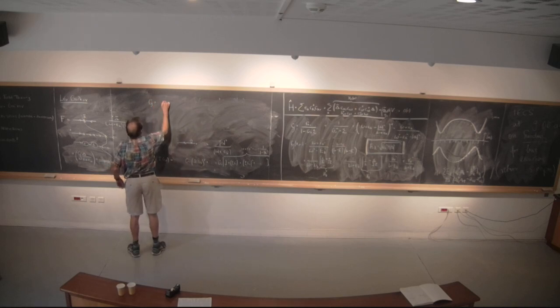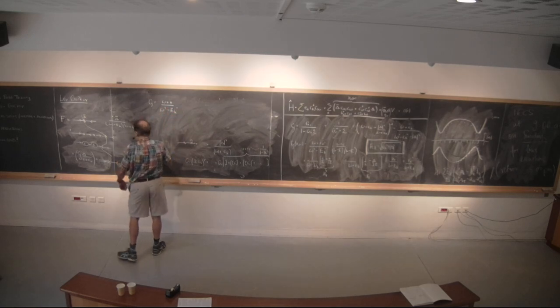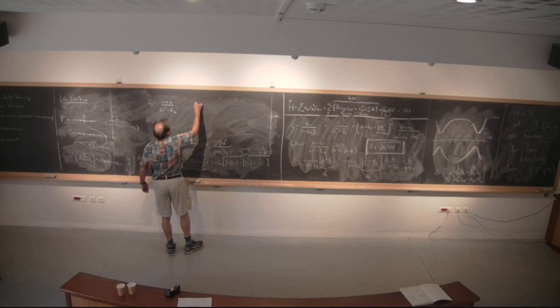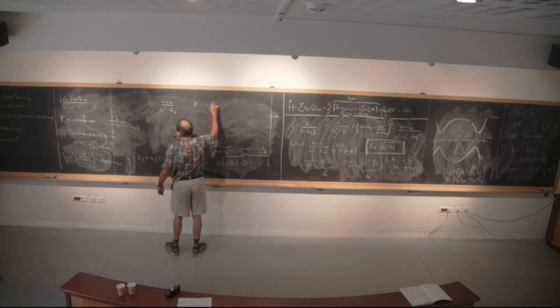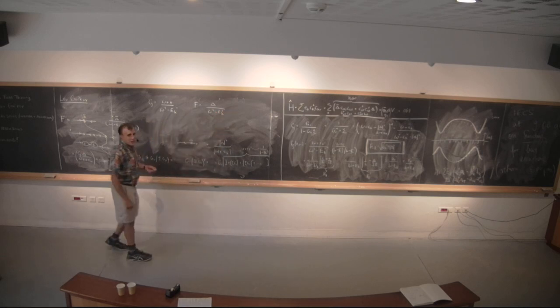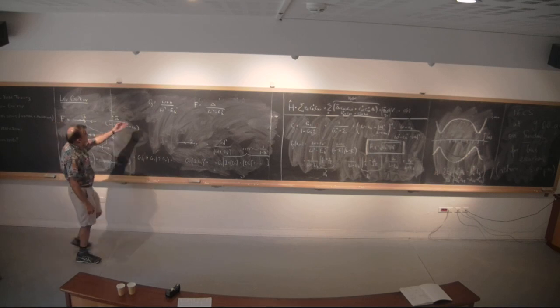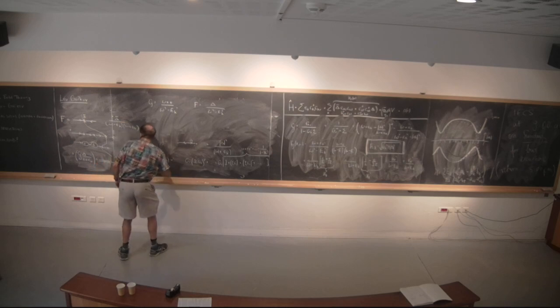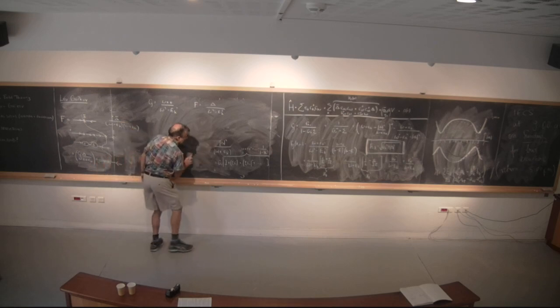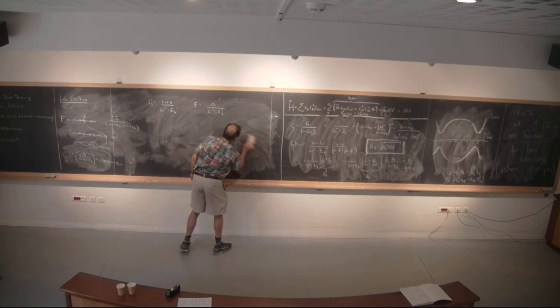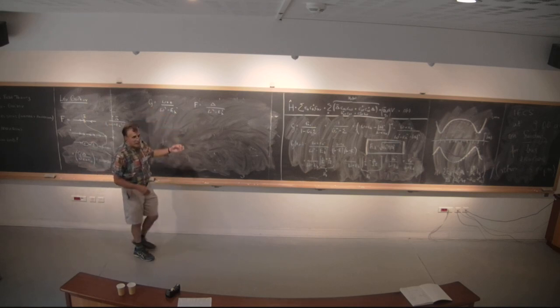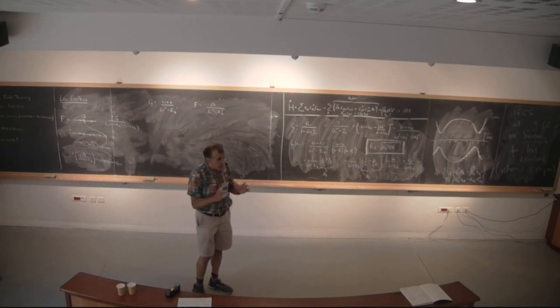This is G. G was (omega plus epsilon k) over (omega squared minus epsilon k squared). And this one here, F, was equal to delta over (omega squared minus epsilon k squared). It looks even more elegant than the first term. But they all have the same poles. They're all governed by the same quasiparticles. Okay? So that's what you can do just drawing pictures. In fact, very soon we'll see that these are two components of a 2x2 Nambu propagator.